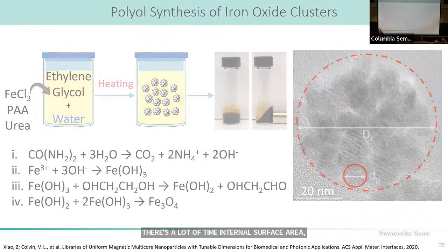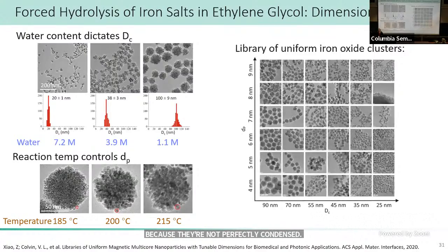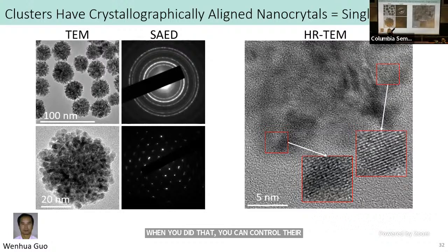When you do that, you can control their size, which I'm not going to talk a lot about. But you can do studies of the crystallography of these packed aggregates. And one of the remarkable things about them is that they are oriented in the same way. So even though this looks like a loose collection of randomly oriented things, it isn't. That orientation process that occurs in this chemistry when they're forming forces the crystal axes to point the same direction. And that oriented attachment, it's actually been known for decades to occur in other oxides, is crucial for what I'm about to show you. So it means that we're able to cluster our particles in a very well-defined way. We don't want big aggregates, but we're able to do so with these holes.